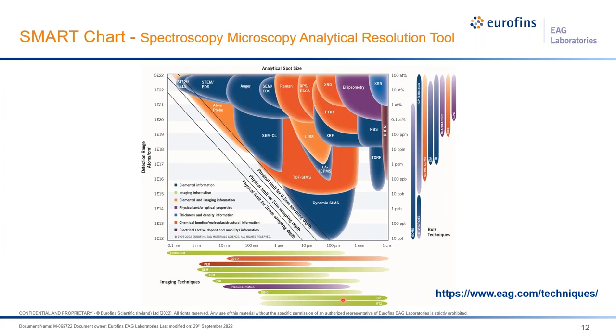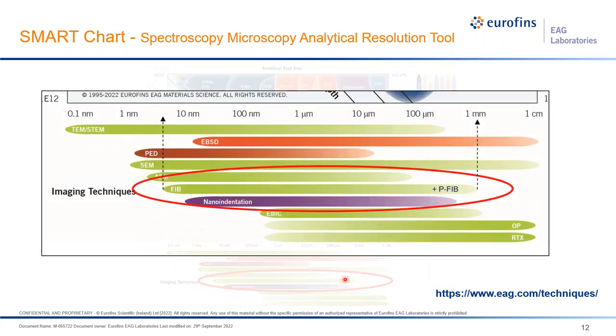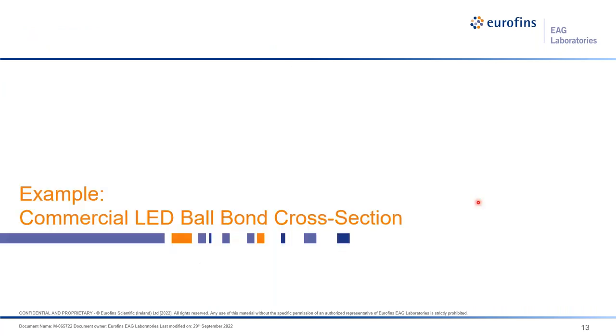This is where we find P-FIB and FIB down here. And essentially here you can see that FIB and then plus P-FIB extends our usable range from sub 10 nanometers out to 1 millimeter. And it's really this extension out to 1 millimeter that we're gonna focus on first here.